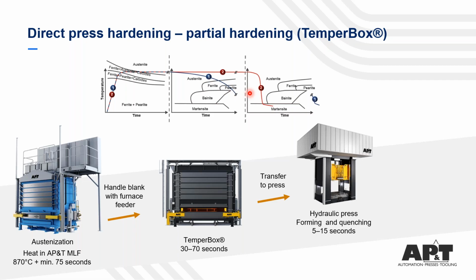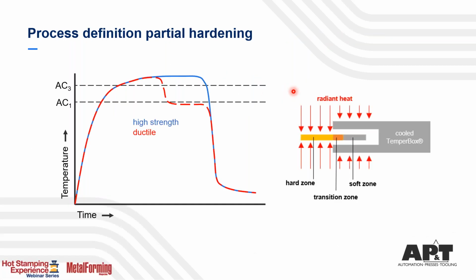After the heat treatment process in the temper box, we conventionally transfer the blank into the press, into the forming die, where we have, again, depending on sheet thickness, a quenching time between 5 and 15 seconds. And what you get is a part with quite localized tailored properties, if you wish so.